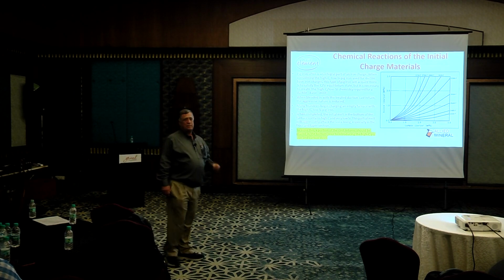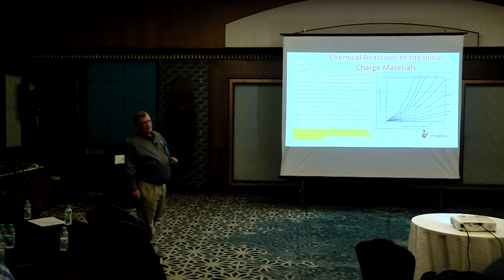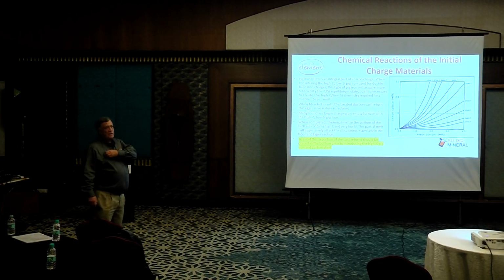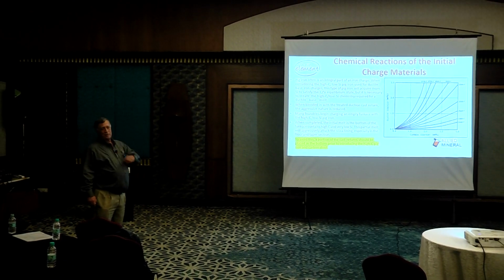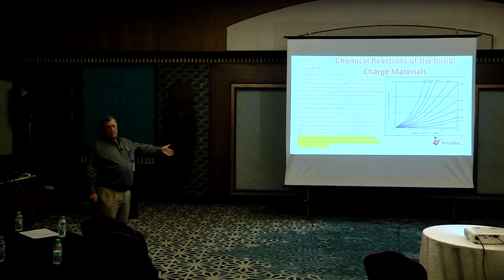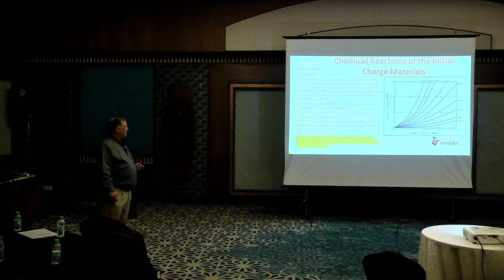Even if you have returns, they say, oh, we can't charge our returns because we don't sandblast them. They're sand. Sand is silica. Additional silica in the bottom of that furnace isn't going to hurt you. You could add ferrosilicon in the bottom, and that would probably help you. So if you have sand on your returns, even if you get buildup in the taper section, I can get rid of buildup in the taper section in 2 hours. That's no problem. But if you erode it, you can't add refractory back.